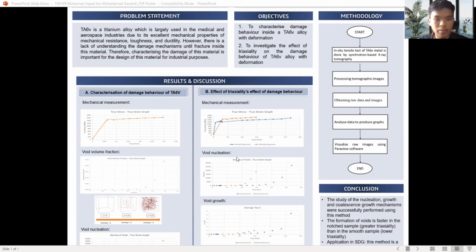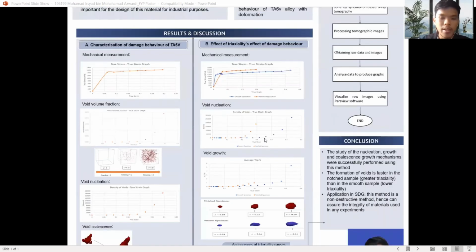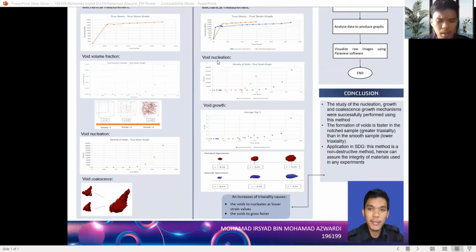Right, let's look at the first graph for this part. The first graph shows the true stress strain graph from both specimens. The notch sample, which has a higher initial triaxiality, has a slightly higher yield stress value compared to the smooth sample. However, the ductility of the notch sample is lower compared to the smooth sample. Next is the void nucleation. It shows the density of voids across the deformation for both specimen geometries, and it also shows that the increase of void density starts at a lower strain for the notch sample.